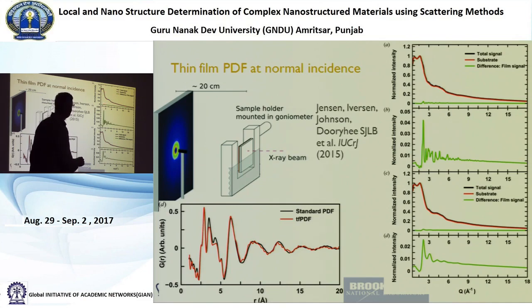But there's a tiny little signal and difference curve. And when we blow that signal up, we get actually a real signal, which is just coming from the film. So a more challenging one, this is where the film is crystalline. A more challenging one is where you've got an amorphous substrate with an amorphous film on it. And that was this case here, and this is the signal we got. And we Fourier transform this signal to get the PDF, and we get the red curve over here.